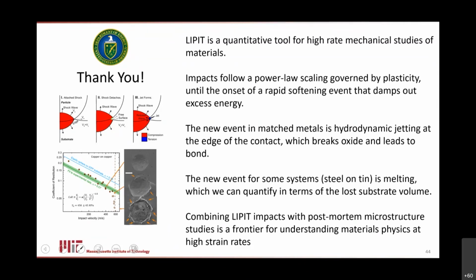Thanks for the great talk. Is there a volume change associated with any phase changes during or after the impacts? So the only phase change that I'm willing to attest to here is the one that I showed you in tin, where we know that we're melting it. The volume change on melting tin is not large, and critically, it's reversible, right? So we don't actually capture the volume change in any of these measurements. We capture it after it's resolidified. So there's no permanent volume change. There's also no reason to expect any solid state changes in any of the materials that I showed you.